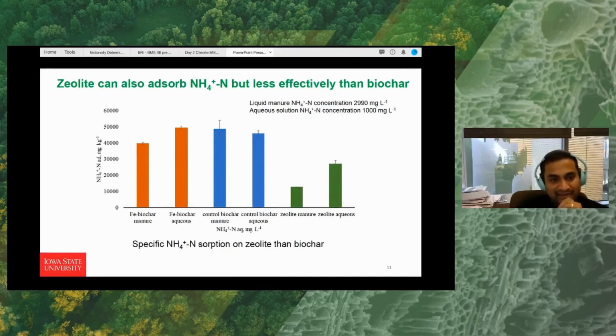So this study suggests that the specific adsorption, cation exchange site adsorption, is happening in the zeolite rather than the biochar, whereas the biochar has more pore space or surface functional groups adsorption compared with the zeolite. Next slide, please.